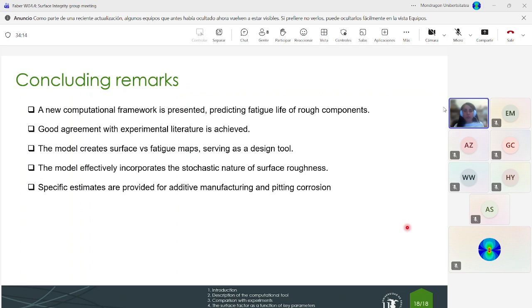We don't include it here, but if you have a look at the paper, you can see that we have used our tool to give estimations for additive manufacturing and also pitting corrosion, and we have checked that it fits the experimental data that we have found in the literature. In fact, for the pitting corrosion, I have a former student that finished his master thesis, and we have applied our numerical tool to study different corrosion profiles, and we have determined the fatigue life of this profile. So we have checked that it works in the end.